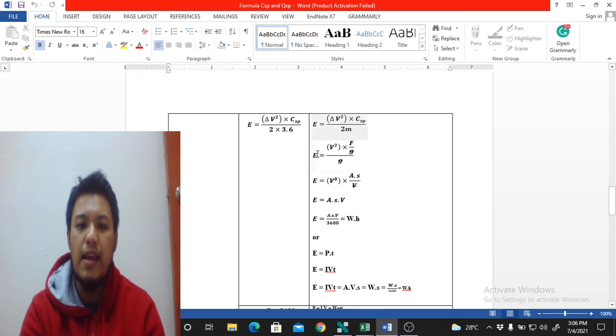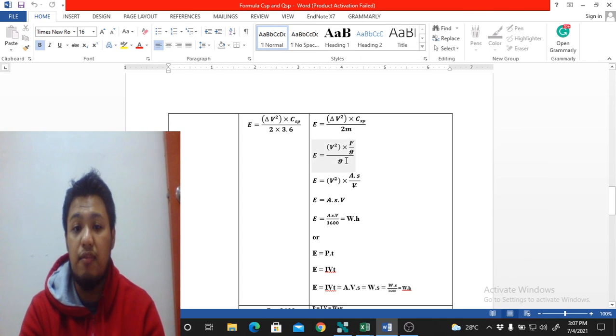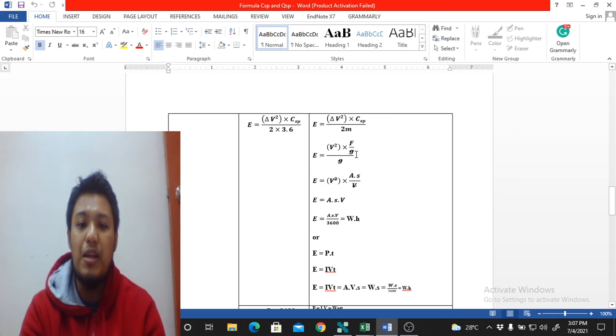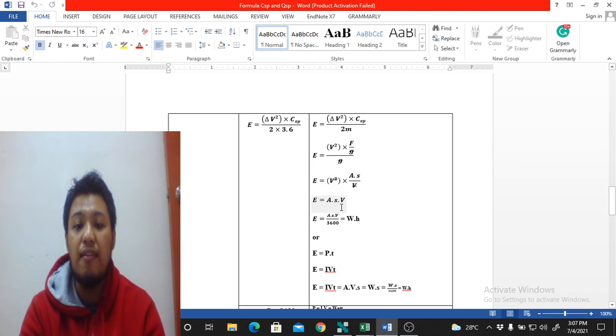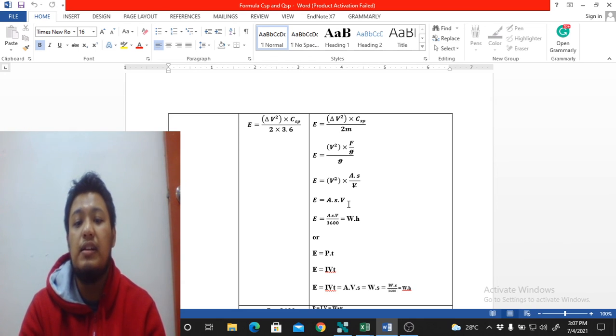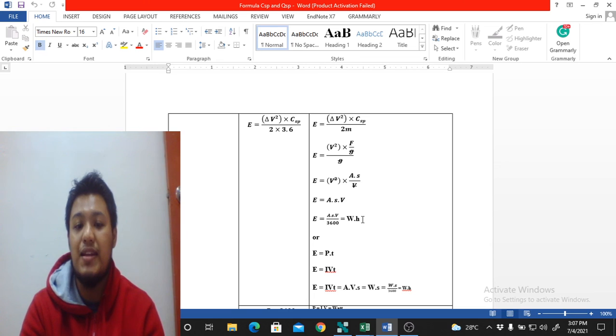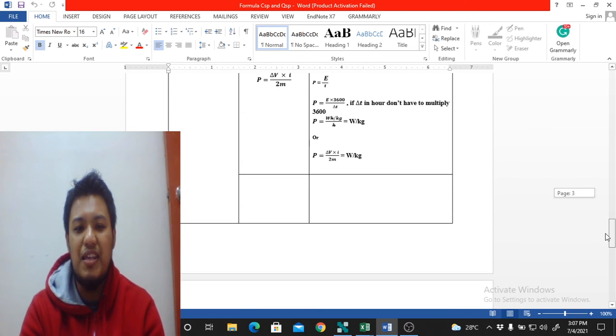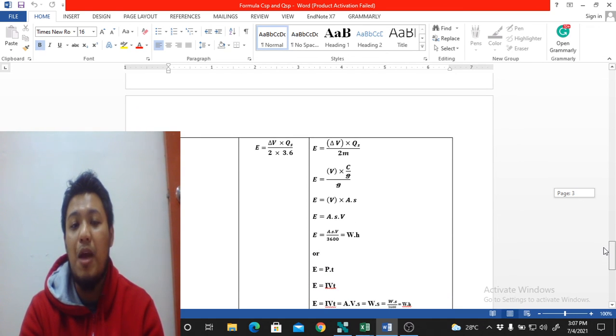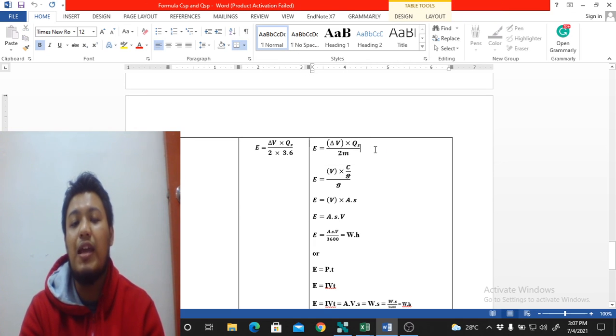To summarize the derivation: E = ΔV² × C_sp / (2m), where C_sp is in F/g. The gram cancels, and using F = A·s/V, we get A·s·V. Dividing by 3600 converts seconds to hours, giving Wh. Dividing by mass gives Wh/kg. For specific capacity materials, make sure to use Q_sp (C/g) instead of C_sp (F/g) in the energy and power formulas.